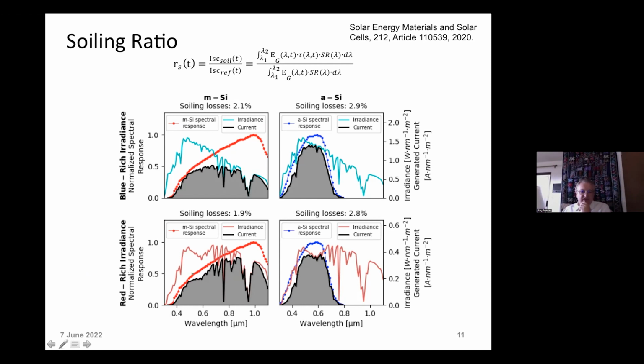If, for instance, the spectrum is red rich, then the resulting product with the transmission, which is not shown here. I have not shown the transmission, but in a minute I will show it. In this case, the result is that during the same day you might have 1.9%. So to impress upon you that the soiling ratio is not fixed, it's due both to the time and to the spectrum. And in fact, if we have time, I'll also show that it depends upon the angle.